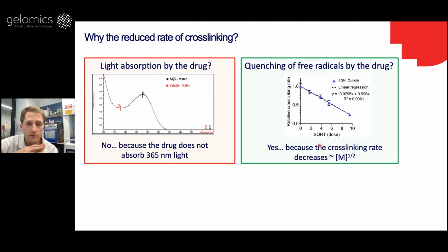is split. So looking at the rate of reaction equations, which I had on a couple of slides ago, you can kind of test that hypothesis, because if it's the case that the drug is quenching, then you'll know that the reaction rate should drop in proportion to the square root of the drug concentration. So to test that hypothesis, that's what we plotted, and we saw a nice agreement.